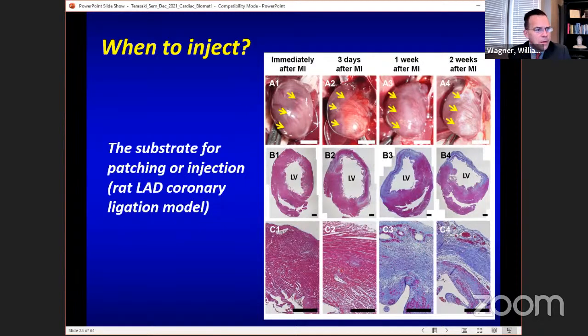So we did a study with the injection comparing the one I kind of poked fun at earlier, immediately after MI. So you do the MI and then you immediately do the injection. So clinically irrelevant, but theoretically, maybe that would be by far the best thing to do because you haven't lost any function, right? There's no function loss right after the infarct. So you inject right at that point. Then we did 3 days after, which we thought was the closest in clinically that might work. We did 1 week and we did 2 weeks.